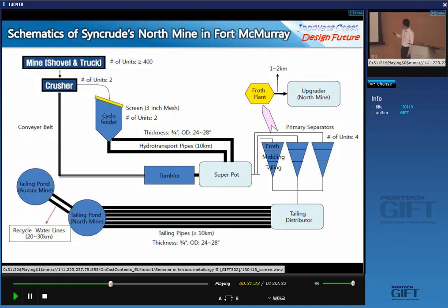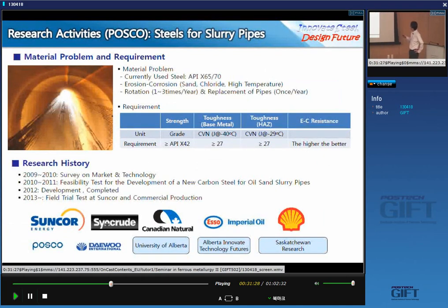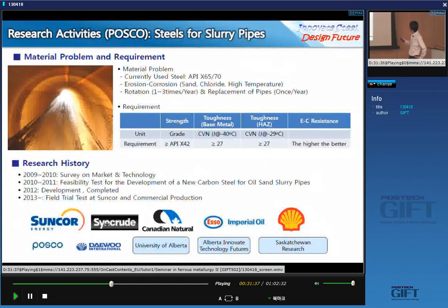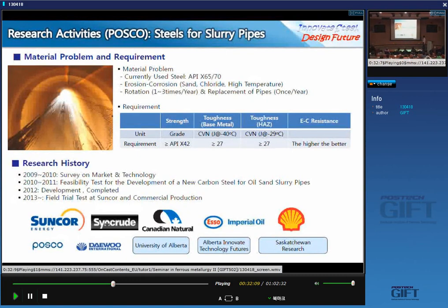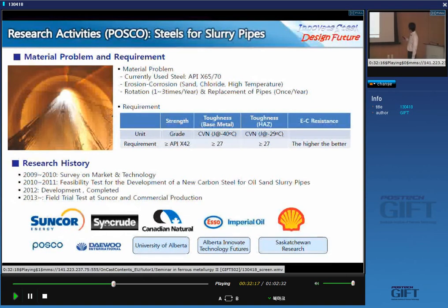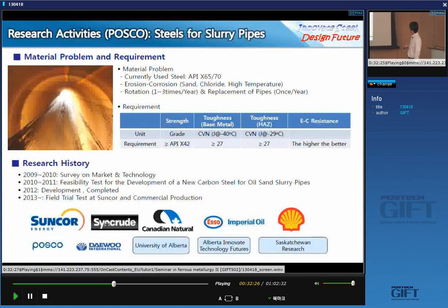The current materials used are API X65 and X70, and the main problem is erosion and corrosion. They have to rotate pipes one to three times a year, and replace pipes once a year on average. The strength requirement for new material is over API X42 grade. They need assurance of toughness of base metal and weld metal at minus 40 to minus 29 degrees Celsius. This is a mandatory requirement for material used in the oil sand business.